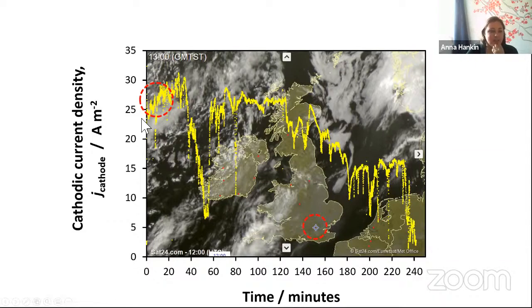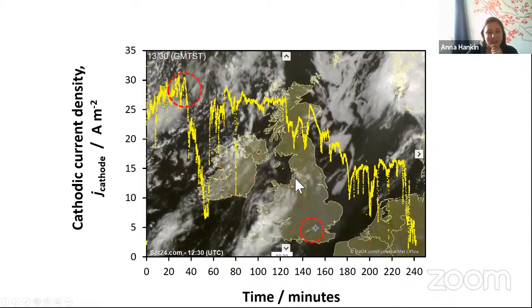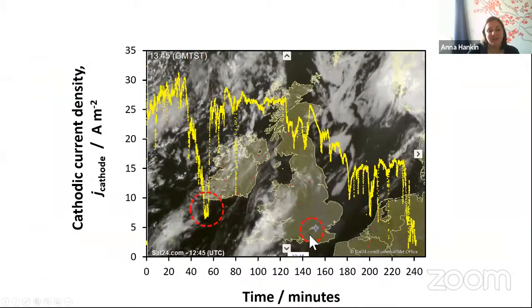We had, with triple junction solar cells, 25 amps per square meter, and everything was great, still great after 40 minutes. But then you can see that there's this tiny, tiny cloud approaching our position. And what happened then was, despite this very slight cloud, I mean, it was a perfectly blue sky, with just this tiny little thing, it had a profound effect on the performance of our device.